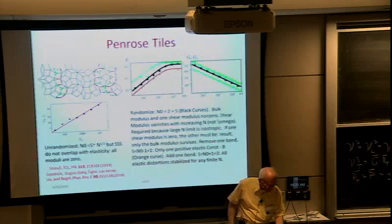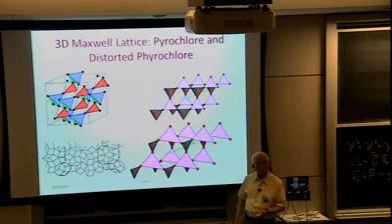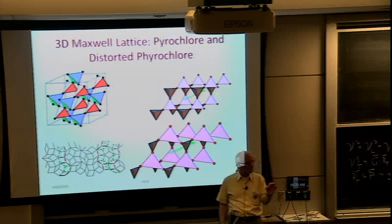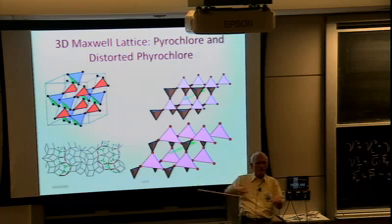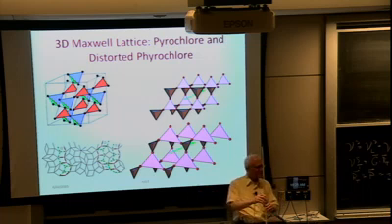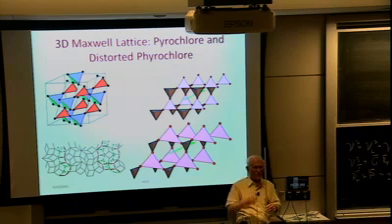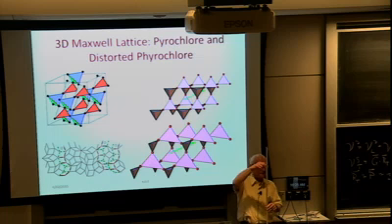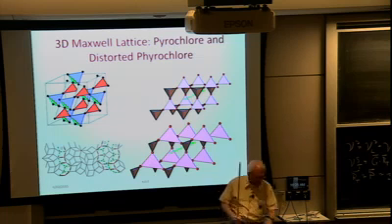If you look at this lattice in 3 dimensions, it's full of Weyl modes, these extra zeros in the lattice, but rather than being just isolated ones, they actually are lines of zero modes. So if you think of the Weyl modes in 2 dimensions as being a vortex in the reciprocal lattice plane, when you go to 3 dimensions, that vortex becomes a vortex line, which is why you have lines of zero modes.